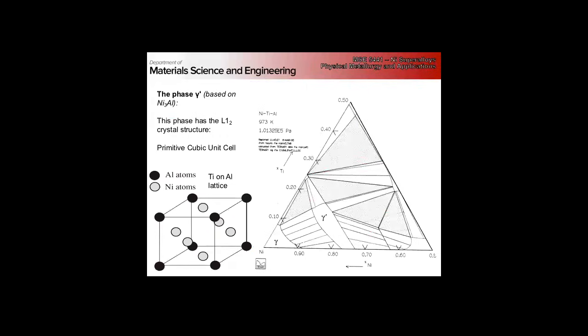Crystallography reminder: this aluminum atom and 3 nickel atoms - that's our motif. Our lattice sites are the corners of the cube. So if we repeat this cluster of 4 atoms, translate it, we end up with the L12 structure.